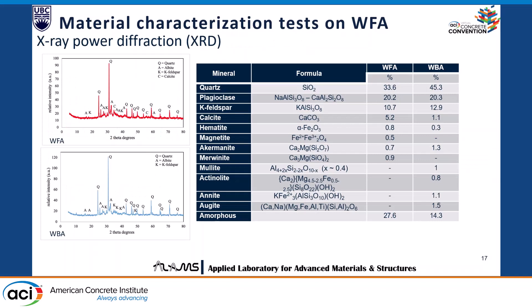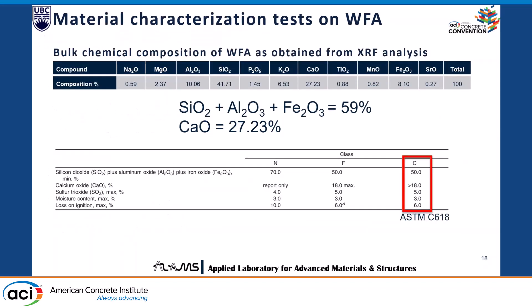These are the XRD results of both the wood fly ash and the wood bottom ash, where quartz was the major element. Looking at the XRF results showing the chemical composition and metal oxides: according to ASTM C618, there are three classes of fly ash. The combined silica, alumina, and iron oxide content is 59%, which could be either class F or class C. However, from the calcium oxide content — greater than 18% — we conclude that our wood ash behaves more like class C fly ash. The sulfur trioxide content was only 1.04%, well below the maximum limit.